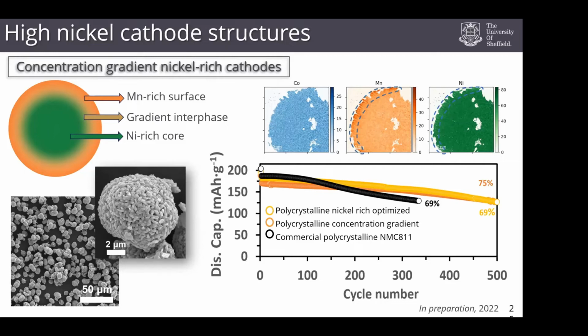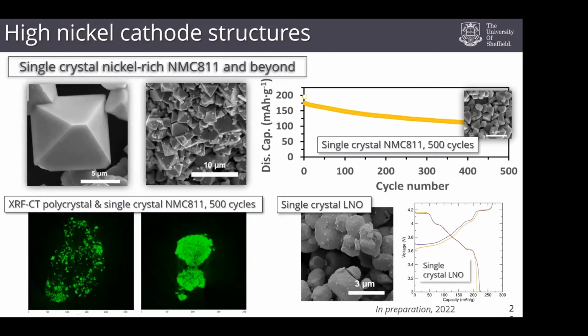So we're working at the moment to scale this sort of chemistry up so that we can make many, many kilograms of material that we can then pass to our friends in Warwick, who can do some large-scale batch testing of these batteries. We're also looking at making high nickel content crystals so that we can try to avoid this cracking phenomenon that can occur. This is showing you really nicely what I mean by that.